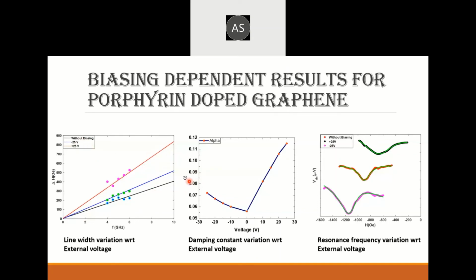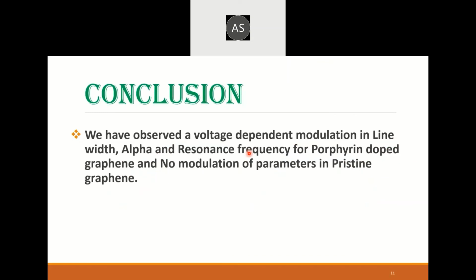And also we have obtained the alpha from here, and we found that this is also following a linear relationship with respect to voltage, and it also gets modulated. Similarly, your resonance field or your resonance frequency also changes with respect to gate voltage. So basically, these are our main findings, and we are doing some more controlled experiments for validating these in a further run. I mean, this is our recent finding about this graphene ferromagnetic interface.